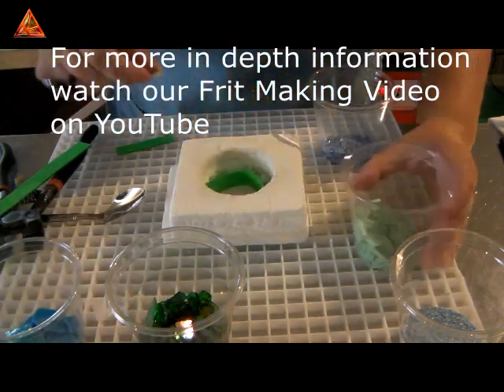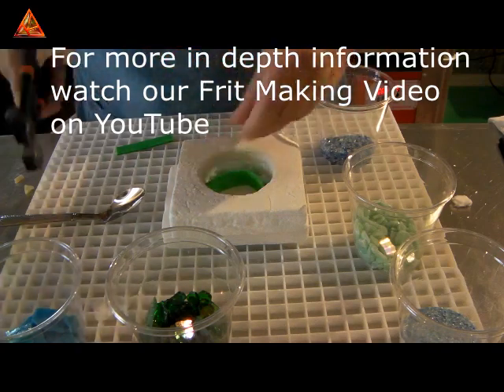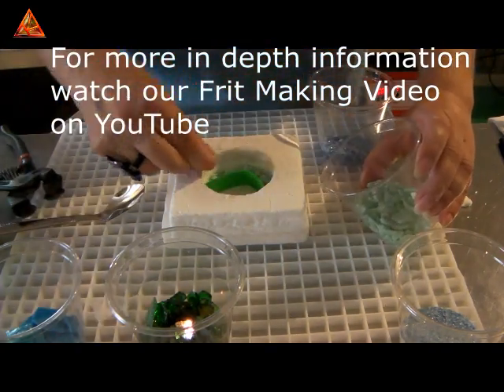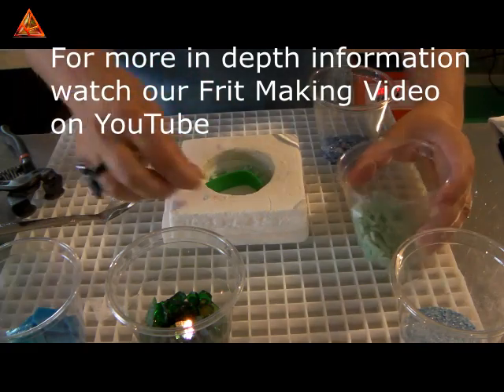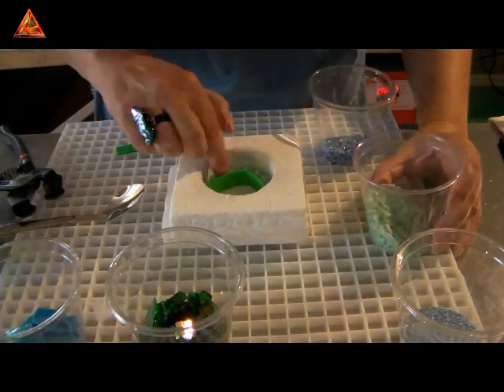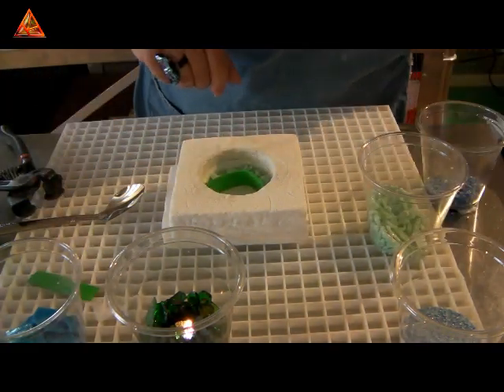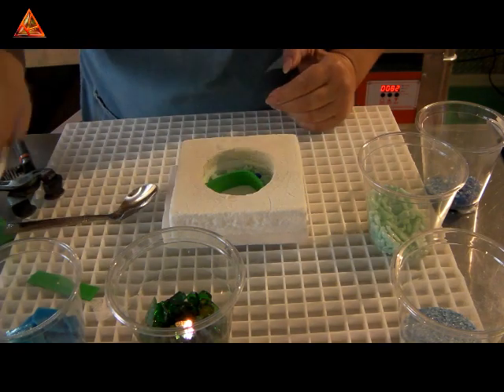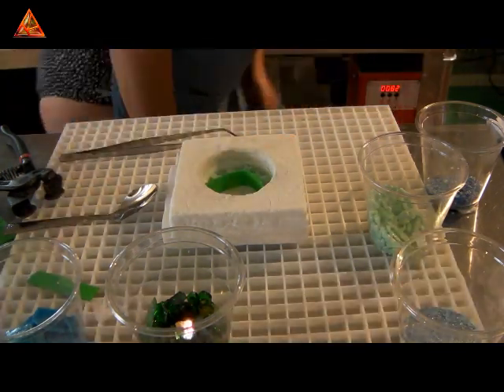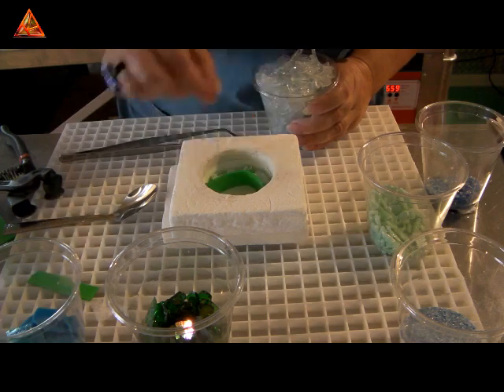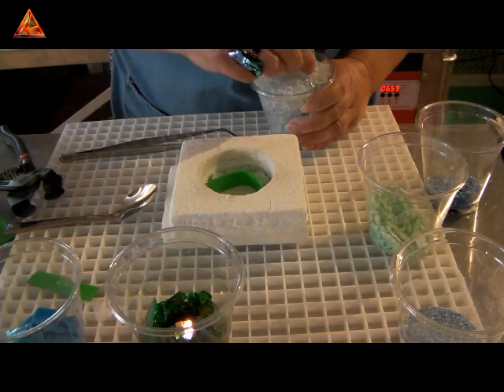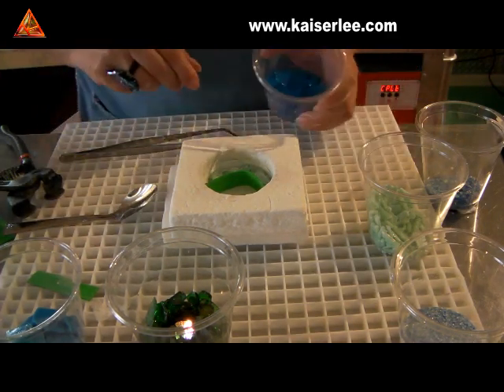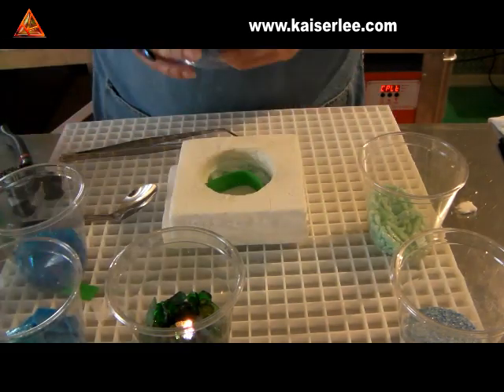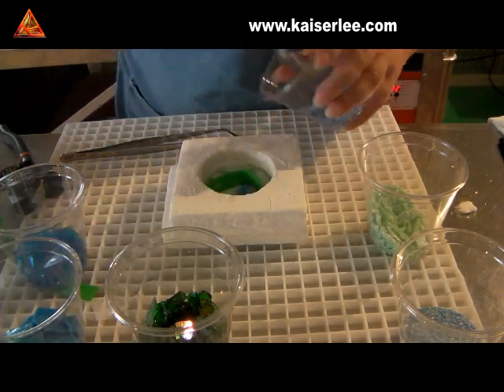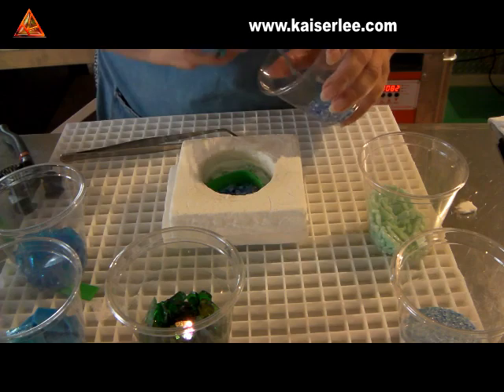Now I can fill the mold with my Cullet-frit pieces, about a 1/2 inch, definitely not higher than my paper strips on the side of the mold. On one side of the foam I used the coarse pieces of Wissmach 9606 pale green, and on the other side I use a mix of clears and blues in a smaller size frit. As you will see in the final piece, it will result in uneven thickness.